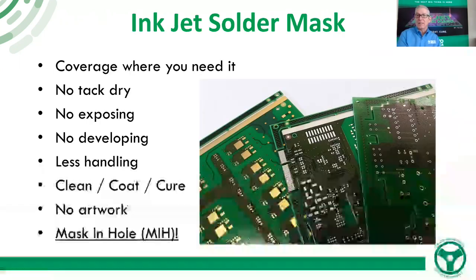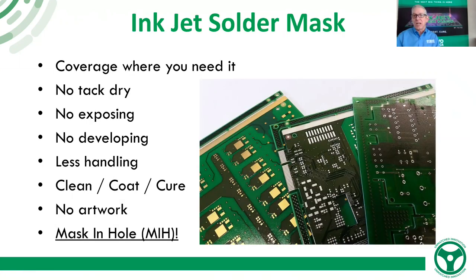So where does that take us? That takes us to inkjet solder mask. Coverage where you need it, fully additive. We're not putting mask in the hole, ergo, we don't have to develop the mask out. We don't have to tack dry it. We don't have to expose it. We don't have to develop it. Less handling. We clean, we coat, we cure.